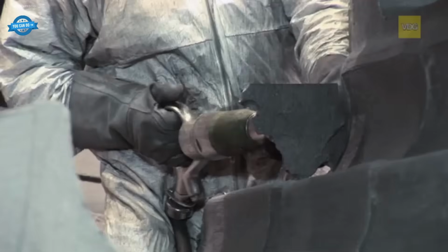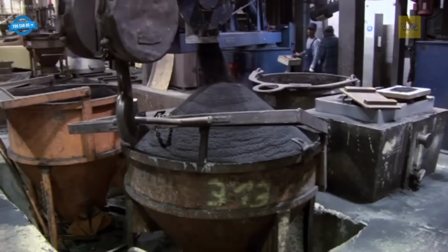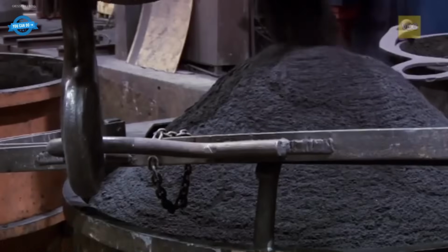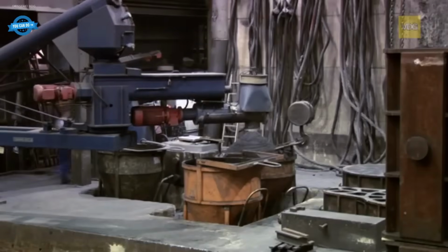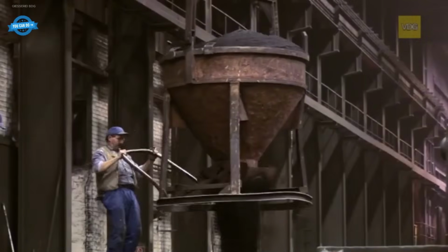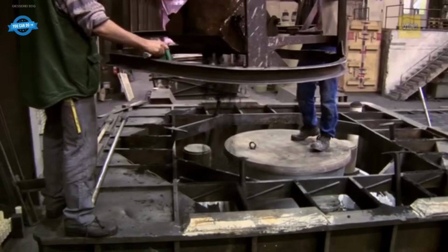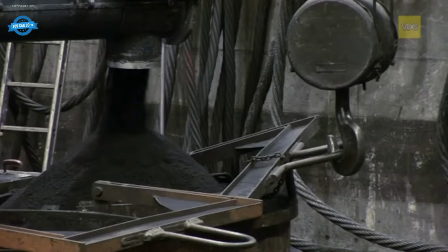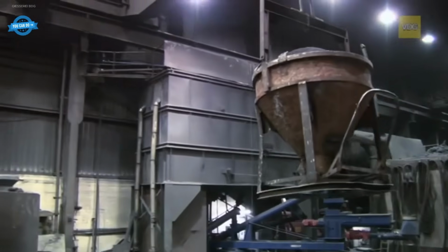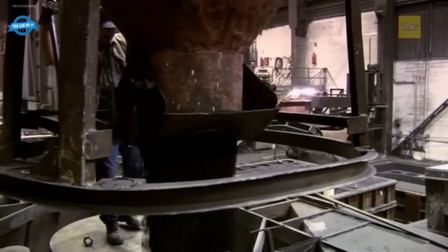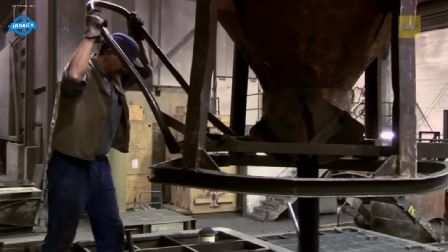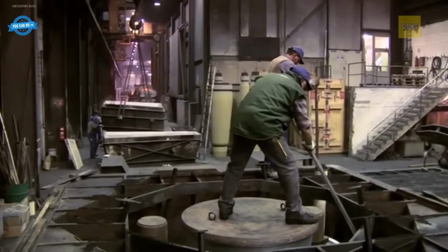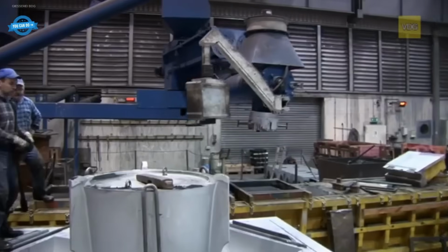The melting process uses cupola, electric arc, or induction furnaces, depending on alloy type. In ductile iron casting, molten iron is treated with magnesium to transform graphite from flake to nodular structure, enhancing tensile strength and elongation. The treatment occurs in converter ladles, where magnesium ferrosilicon is introduced under cover slag. The process produces a bright flare as magnesium reacts.